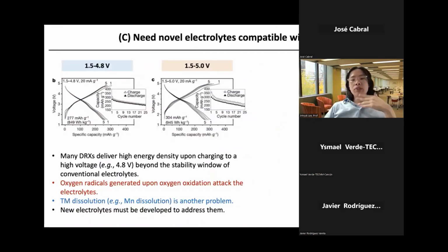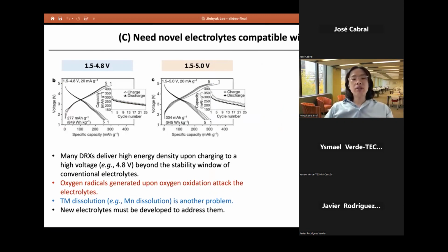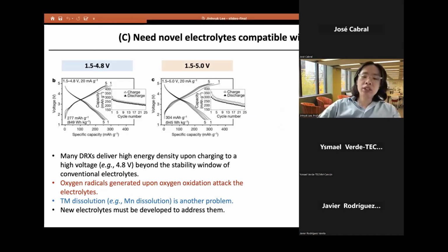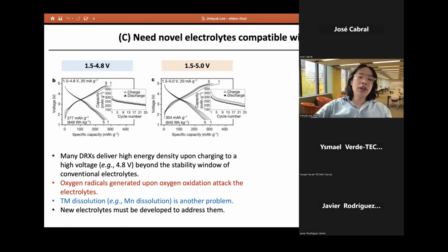And finally, I would like to say that many of the DRX materials deliver high energy density when charged to very high voltage, up to 4.8 volts, which is beyond the stability window of the conventional electrolyte. And I've discussed that the oxygen oxidation generates oxygen radicals that can attack the electrolyte, and there can also be some transition metal dissolution problems. So overall, we have to say that there must be some compatible electrolyte to further address this issue. So our group is also working in this research direction.